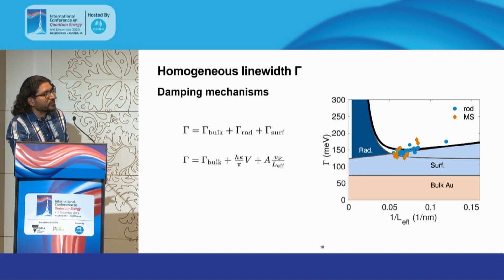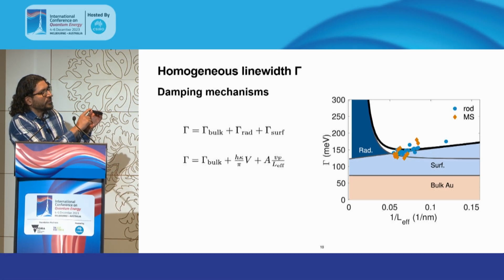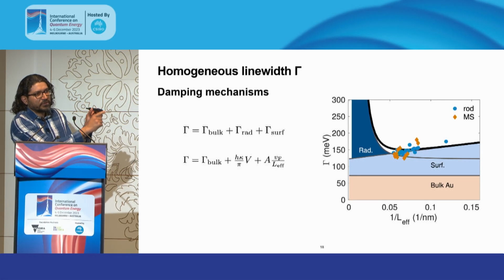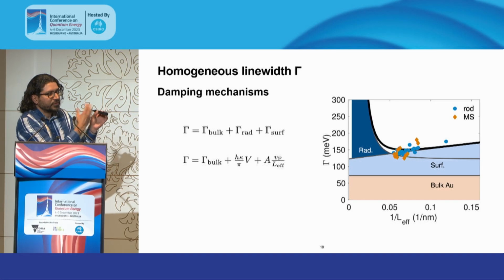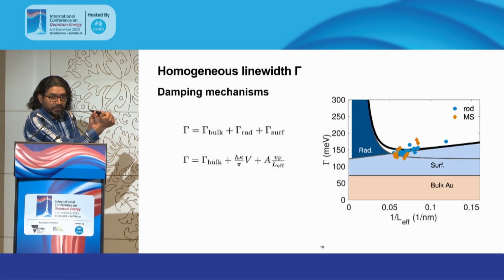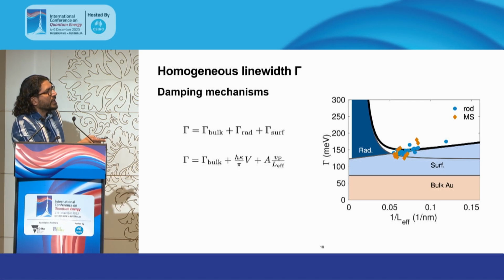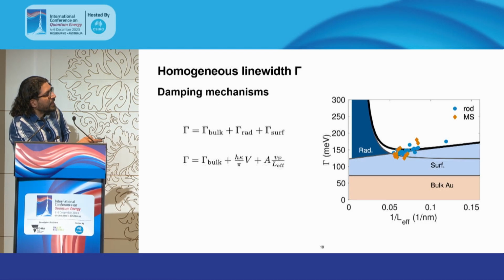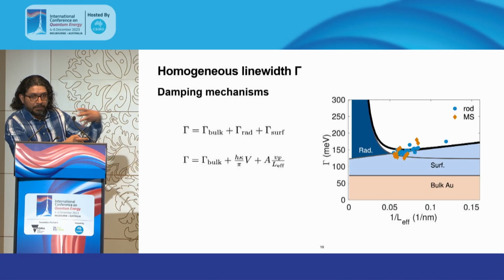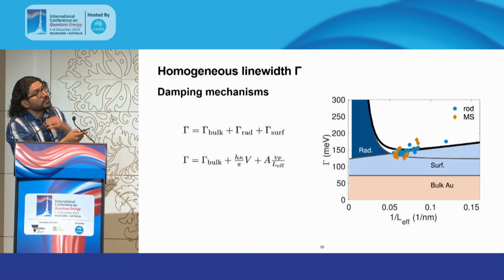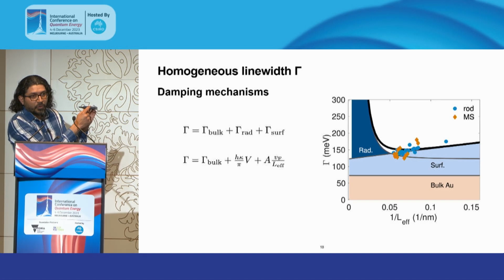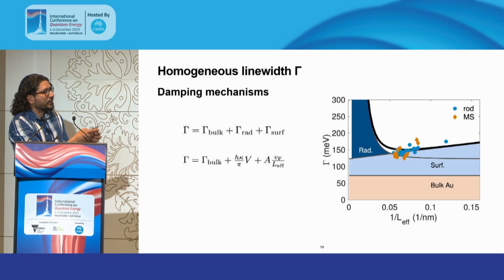The next term here is surface scattering. So processes that take place along the surface of the particle that lead to plasmon damping. If the electrons are oscillating and all of a sudden they get trapped at one end of the surface, then you'll get a lot of damping. This damping is proportional to the Fermi velocity of the electron, the surface charge density of oscillation, and it's also dependent on the average distance of the electrons to the surface of the particles.